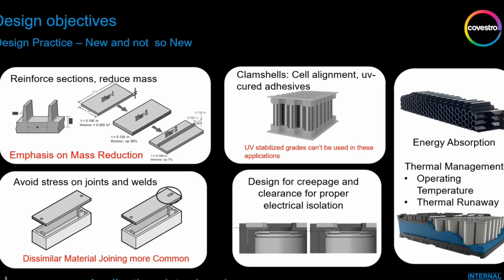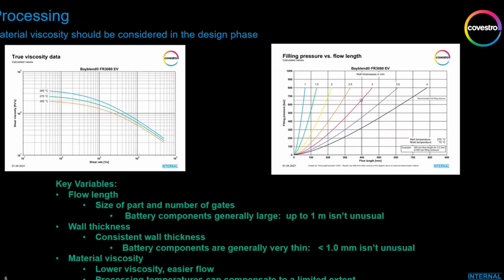Matt mentioned our energy absorbing materials. We also have a design factor there as well. The materials themselves, especially the macro blends, have great energy absorbing potential, but the design is critical. The height of the features, the diameter of those crush towers that you see in this picture, and the material properties all work together to absorb the energy of impact properly and to give you your best performance. And then finally, too, there are thermal management considerations. And you'll see going forward here, we have some materials that are not only polycarbonate based, but they're thermally conductive and can help with thermal management of a battery system.